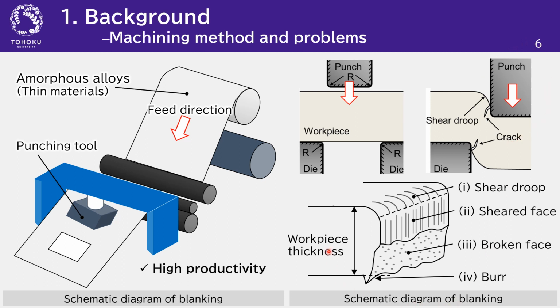This is a schematic diagram of the fracture surface of blanking. First, shear droop is generated by shear deformation, and next, a sheared face is created by friction with the tool. And when the material yields, a broken face appears due to the propagation of cracks, and machining defects such as burrs appear on the bottom surface. Amorphous alloys have high strength and toughness. This property causes excessive shear droop and severe tool wear.